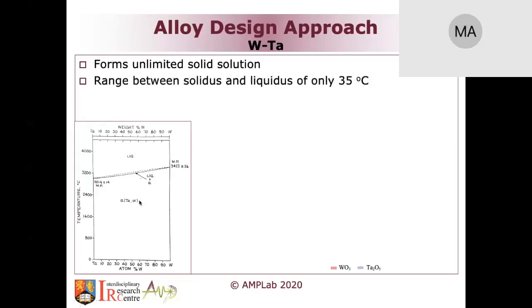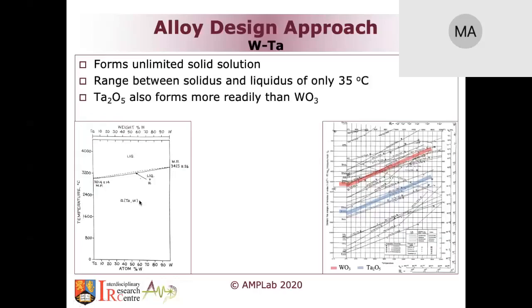And also, from a point of view, tantalum has an oxide, which is tantalum pentoxide (Ta2O5), the one appearing here on the Ellingham diagram in the blue line. This is the tungsten oxide, WO3. Now, the tantalum oxide will form more readily than the tungsten oxide, meaning that if there was excess oxygen, tantalum would happily suck it up and will prevent it from going into the tungsten.